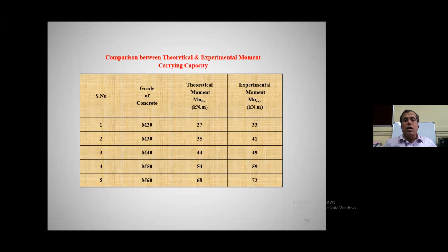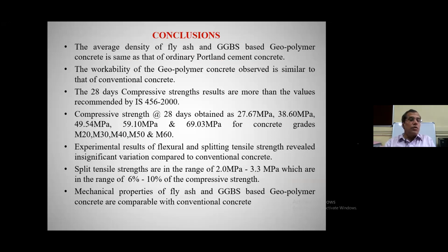So in all cases, all grades, theoretical is less, experimental is more. This is always good, so we can say that our design is correct. This geopolymer concrete, with the ingredients and the characteristics, the values we obtained are really meeting the target strengths of all the grades. Now I have shown only up to M60 because the 70, 80 results are not out. It takes some time to consolidate them. Our students are doing it. So this is the improvement which is taking place. That's what I thought I should share with you all.